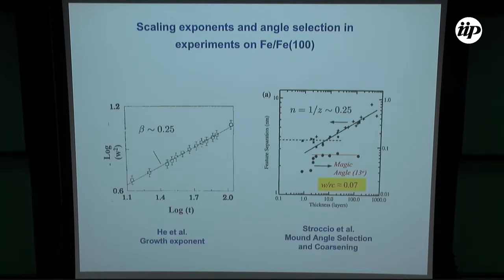I'll show you another one. This is, I think, iron and iron. Yeah, this is the iron and iron experiment of Stroccio. The width grows roughly at 0.25. This is W squared, so this is not 0.25. This is not a half, but beta is about a quarter. N is about a quarter. And again, the angle, you can see, is selected after a few layers.